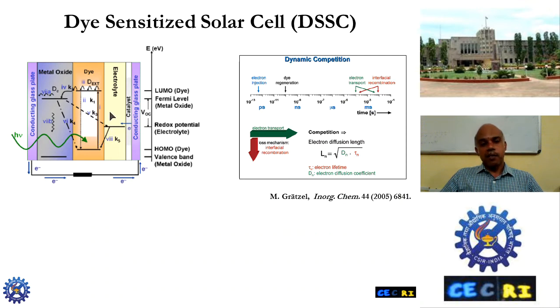However, there are other drawbacks of this. There is a recombination of this excited electron, which can combine with the electrolyte, which can also penetrate through the mesoporous layers of this metal oxide, or this electron can come back to the HOMO level of the dye. So for this DSSC to work, there should be alignment of the energy levels. For example, to regenerate the dye, the HOMO level of the dye should be at a much more positive potential compared to the redox potential of the electrolyte. That means the electrolyte should have more reducing power to reduce the oxidized dye molecule. And again, the conduction band level of titanium dioxide should be just below the LUMO level of the dye so that the electron transfer happens.